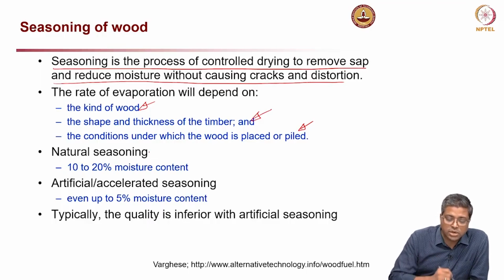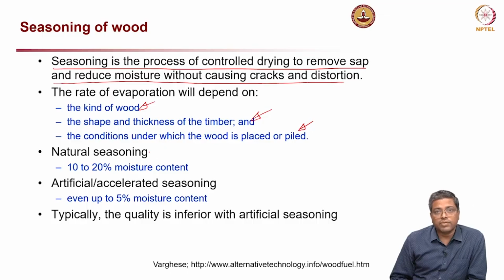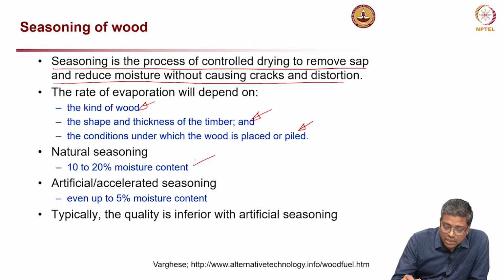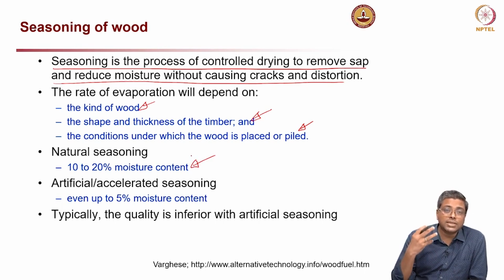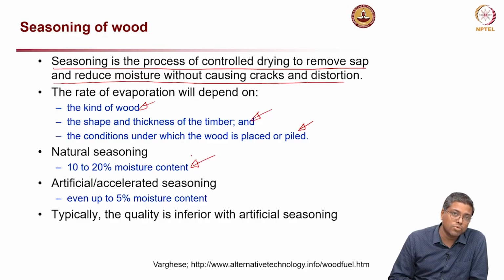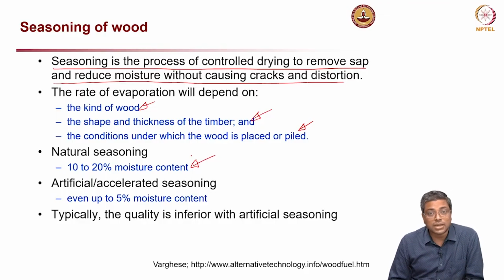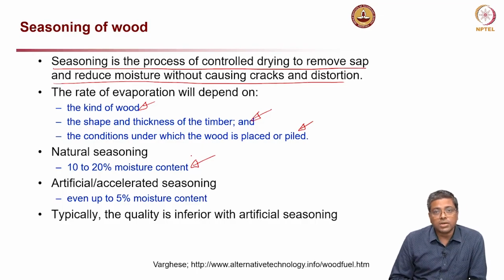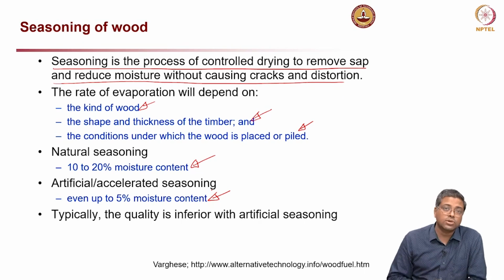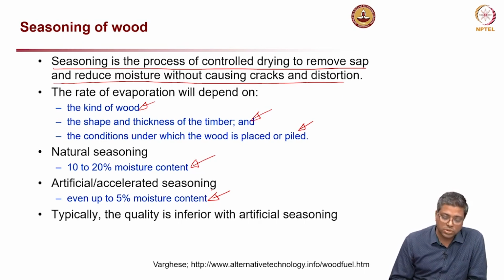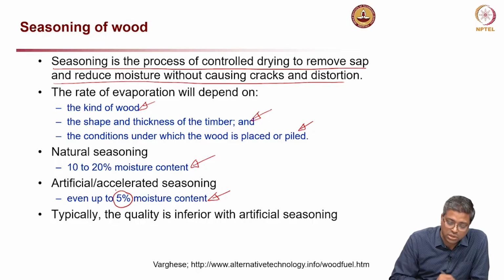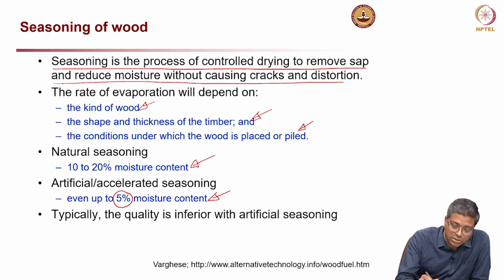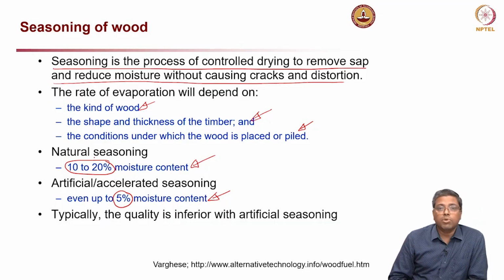Now natural seasoning is one way, and another way is artificial or accelerated seasoning. With natural seasoning, you can remove about 80 to 90% of the moisture from wood, but it takes time. In the case of artificial or accelerated seasoning, you can remove even up to 95% of the moisture, so the remaining moisture content is only 5%. In the natural seasoning case, you can have about 10 to 20% of moisture content.